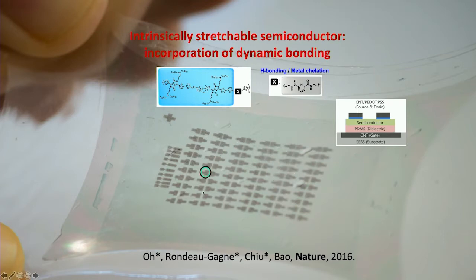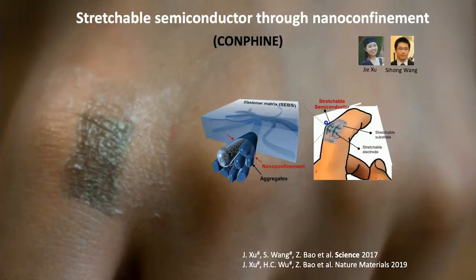So this is an array of such stretchable transistors that's made entirely with stretchable materials. And this is another version of such semiconductor. So you can see this is what it looks like, ultra thin, conforming to the skin. And this is a new design concept that we found, that essentially by induced spontaneous phase separation into the semiconductor and the elastomer blend, we can induce nano confinement into the semiconductor. That actually reduces the glass transition temperature or softens these materials significantly. And this allows us to essentially now take any high performance polymer semiconductor and make it highly stretchable and maintain the very high charge carrier mobility.